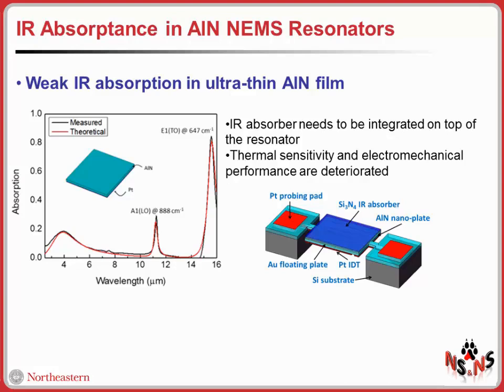The conventional approach to solve this issue involves integrating an absorbing material or a material stack, for example, lossy dielectrics like silicon nitride or a metal-insulator-metal grating on top of the resonant device. That approach improves the infrared absorption of the device, but also typically degrades the electromechanical performance and the thermal sensitivity of the device. As I showed you before, what we really want to do is scale the dimensions, make the device as small as possible, maintaining the high quality factor and transduction efficiency. So this approach goes a little bit against that trend.